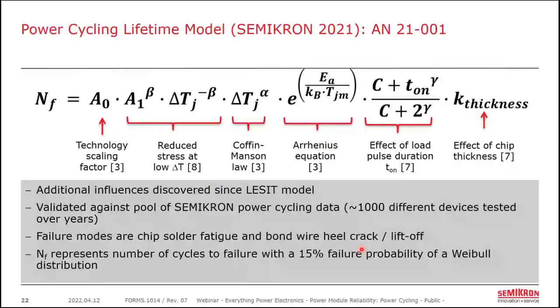There are curves that exist on the market that have been estimated, but like I said, the primary problem is that just doing the test is very time consuming. It might be 6 months worth of testing before you get data to validate that. Now, we do longer term temperature cycling, like we discussed earlier. That's closer to what we would call power cycling, where you're putting the module in an oven. But I guess the short answer is, you push the model as far as you can go.